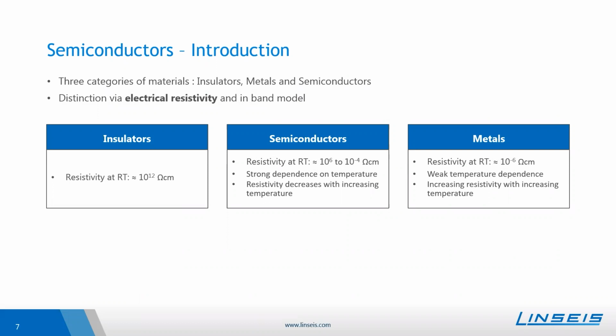Yes, so in general, there are three categories of materials. These are insulators, metals, and semiconductors. These can be distinguished on the one hand by the resistivity and the difficulty of passing current through the material under the influence of an electric field. So insulators have a resistivity at room temperature of about 10^12 ohm centimeter. Metals have a resistivity of about 10^-6 ohm centimeter or lower. And in between those both, there are the semiconductors with typical resistivity at room temperature from 10^6 to 10^-4 ohm centimeters.